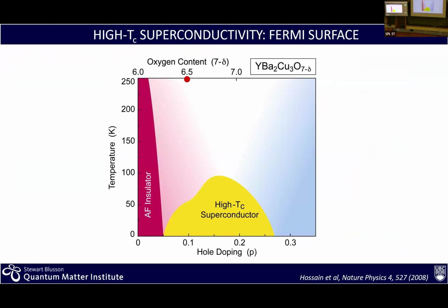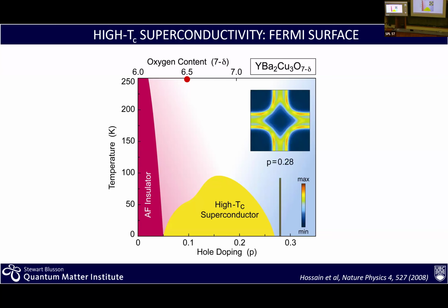And then what we look at, going back to the phase diagram, is now the Fermi surface. We can start on this side of the phase diagram where you have more conventional metallic behavior. As I showed you before, the Fermi surface is basically a contour that can close, separating occupied from unoccupied states. In this case, what I'm showing here is a Fermi surface over one unit of symmetry in momentum space. It's called the Brillouin zone. But if you imagine replicating this Brillouin zone everywhere, here is where your closed contour would be. In fact, this system has two Fermi surfaces, one here and one bigger.